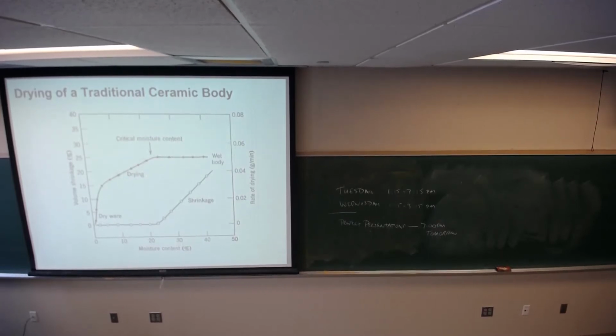Then you get the first falling rate period, which is here, and then the second falling rate period is elimination of the water and the meniscus between the particles. Right, that's your most difficult to remove and takes the longest time. Okay, ideally. So this is critical moisture content, and then this is your end of shrinkage, and they're pretty much at the same place. So you're going from the pores being filled with water and particle rearrangement, which can be significant in the drying process, to a body in which you have only small amounts of water left in the system, and that amount of water basically is just holding the particles together more or less, and then it's being removed in the last stages through evaporation and then diffusion out through the pore structure.